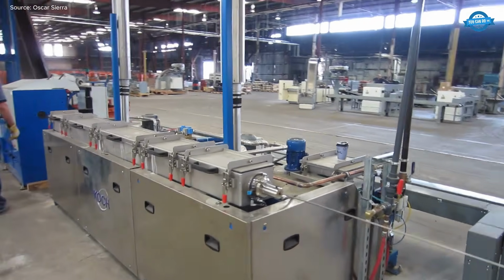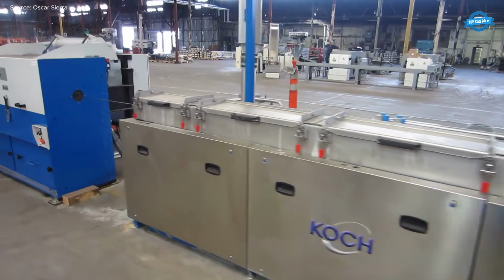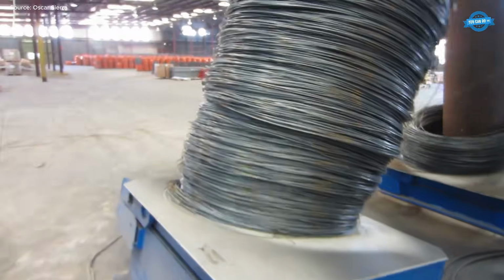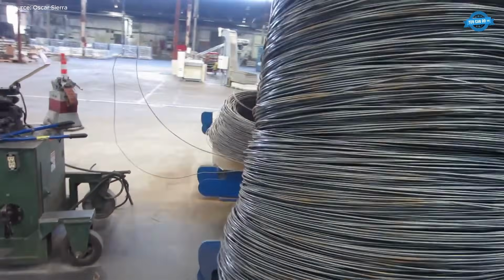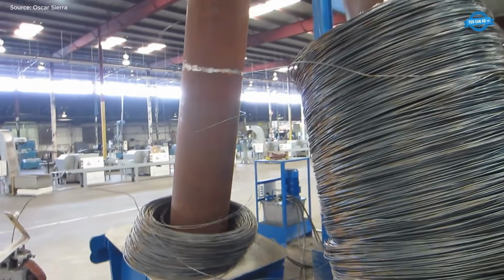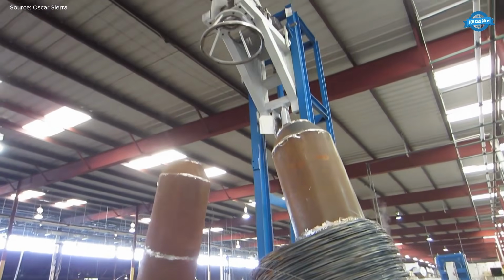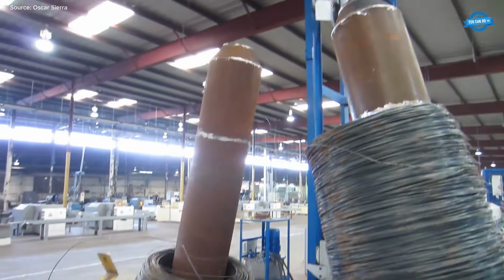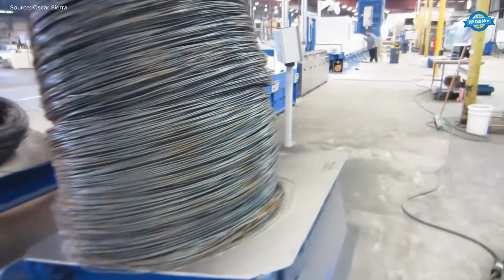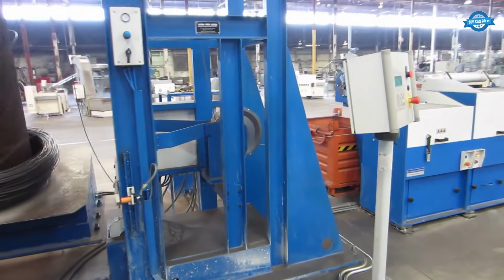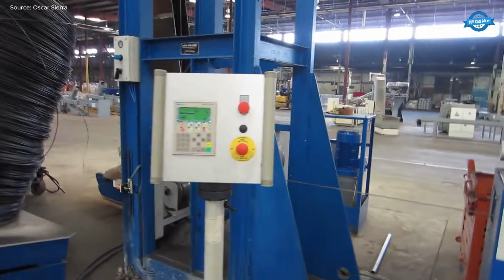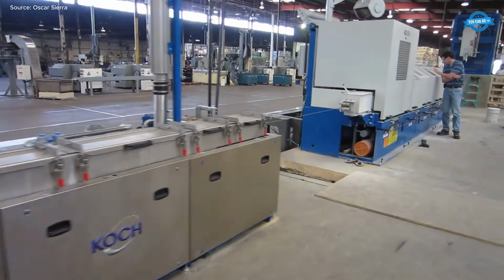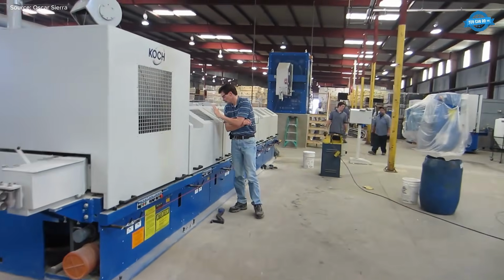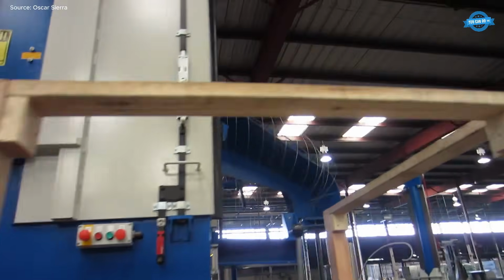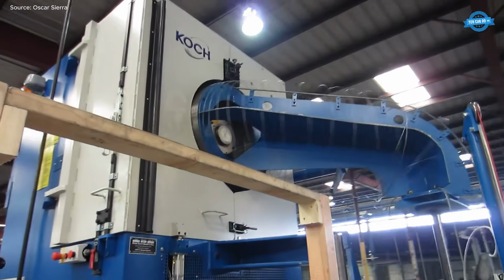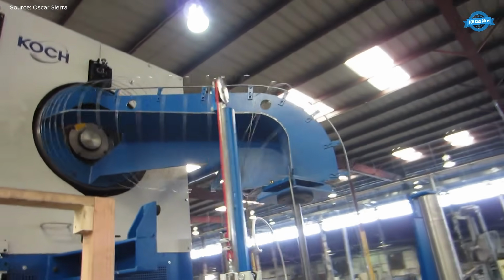The wire is pulled through a series of conical dies, typically tungsten carbide or PCD, each reducing the diameter incrementally. Drawing tension must be managed carefully with servo-driven capstans and tension sensors to ensure uniform strain distribution. Real-time diameter monitoring ensures product consistency, while continuous cleaning systems remove oxides before drawing. By optimizing die design, lubrication parameters, and mechanical calibration, existing machines can reach near maximum productivity. This reduces downtime, tool wear, and energy consumption, enhancing product quality and delivery reliability without additional investment in new machinery.